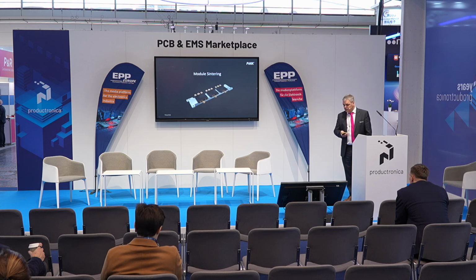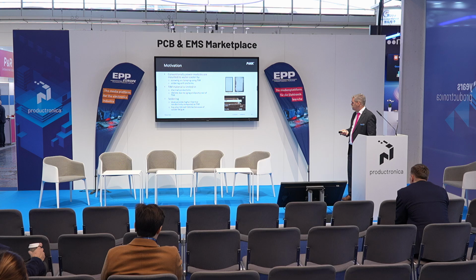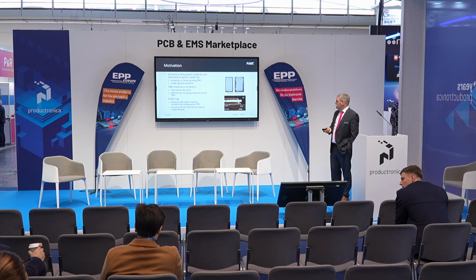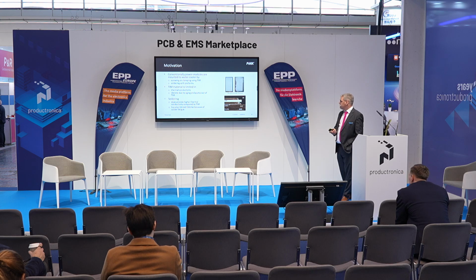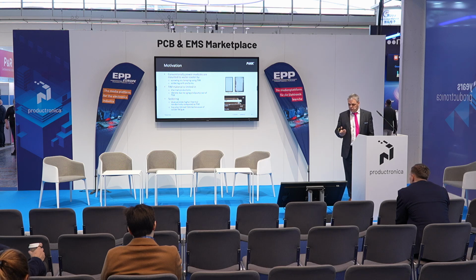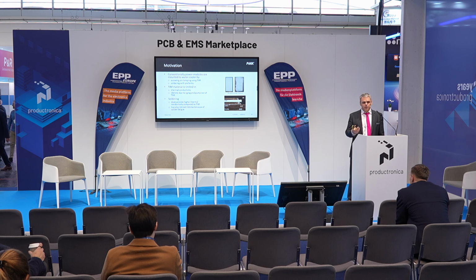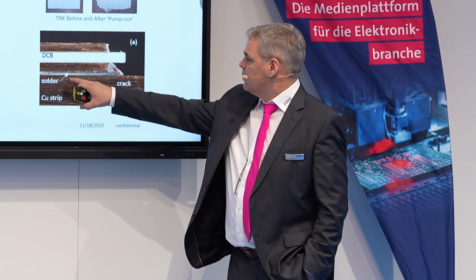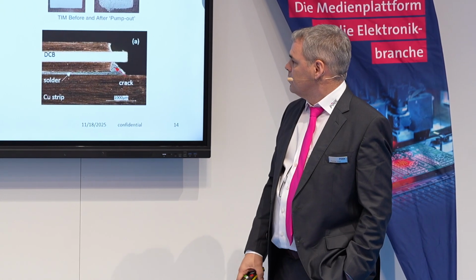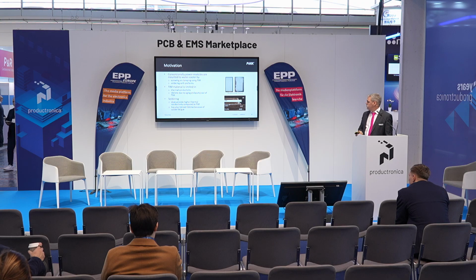But let's go back to the module sintering. Why do we do that? As I said, reliability is key. Looking at today's technology, we sometimes use even TIM, thermal interface material, which has an issue of pump out. So the thermal performance of that technology will degrade over time. What Mr. Feo also introduced, you may see a little bit, is a soldered layer here, and after thermal cycling we can see a crack here. And for the thermal interface material, we also have the issue that the thermal performance of that material is not that good.